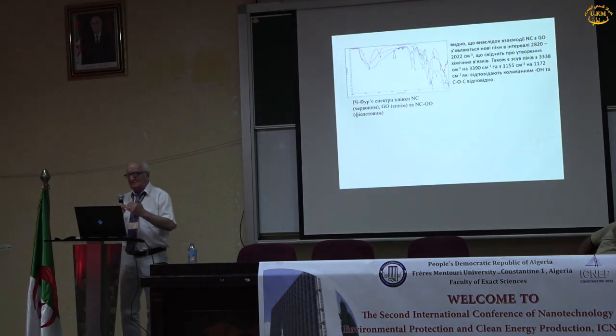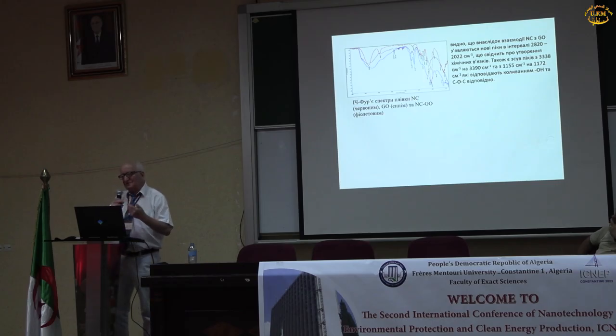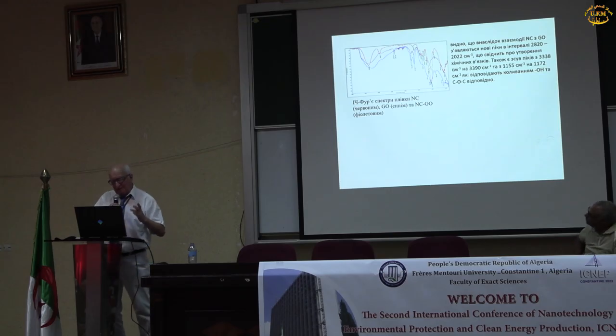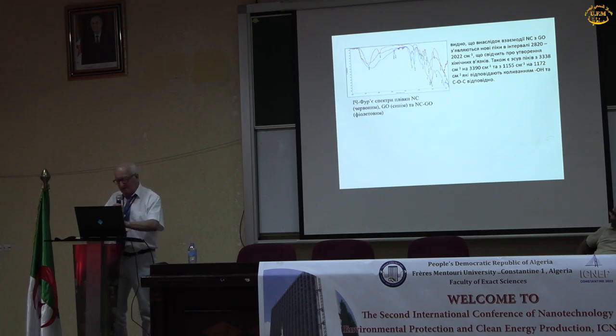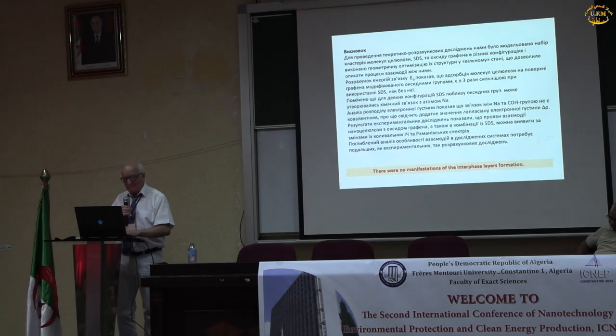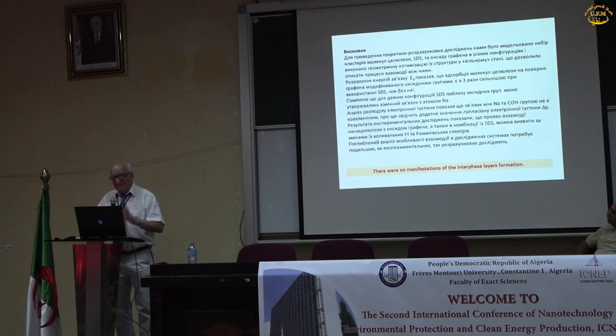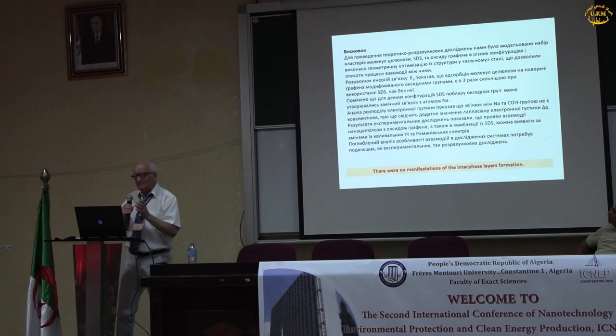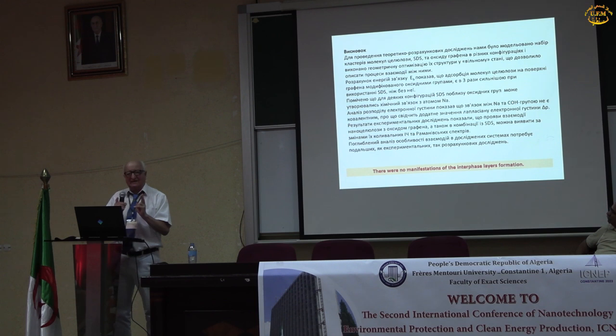Then we aimed to find the manifestation of interaction between the matrix and cellulose, between carbon nanomaterials. We provided Raman and infrared spectra, and we see some changes of the structure that reveal the interaction between these components. In this study, we did not find the manifestation of an interface layer. We see also the interaction between components.